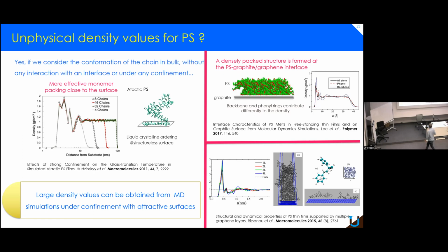But what I'm saying is that here they are able to find very high values. I agree that it's closer to the interface, but at least here they find something related to that. The explanation is that because of the interaction, the polymer can be somehow packed or layered, giving rise to higher density. So I will not argue with higher density. I will just argue with the variation of density, which is easier to struggle with.